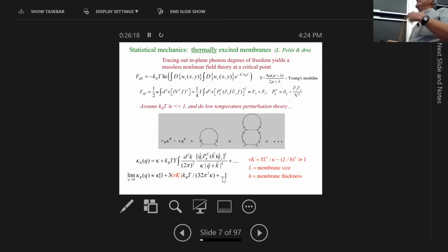And if you do that, you get a self-consistent equation. You get a Dyson equation, fancy name for it, for this renormalized bending rigidity, where it occurs on the left-hand side, but also on the right-hand side in the denominator. And then you get a self-consistent equation that you solve for this renormalized bending rigidity as a function of wave vector.